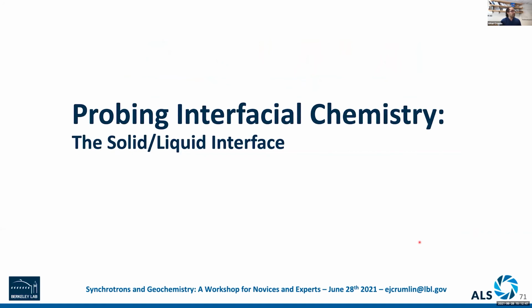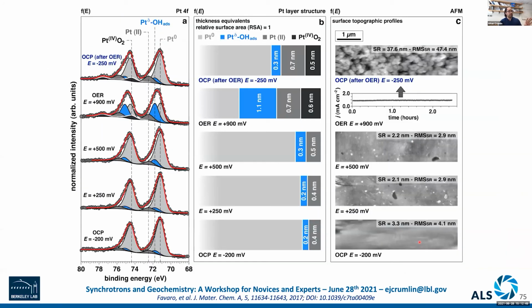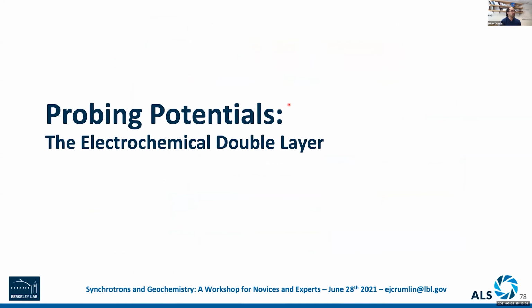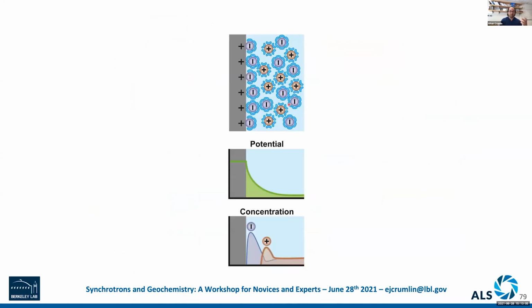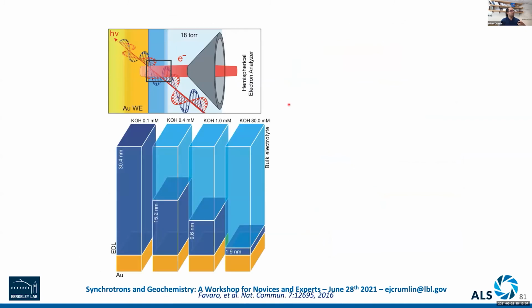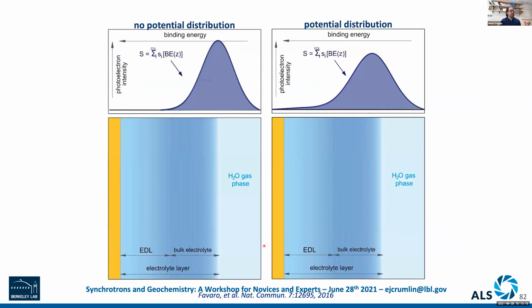And so I'm going to skip through this one, but essentially this is looking at the platinum electrode doing water splitting, where we can quantify the different thicknesses of this layer as it's evolving and get a clear picture of what is happening as it's all changing spectroscopically. And what I want to do is go quickly to the electrochemical double layer. We can sense potentials. If we use this technique and we create different thicknesses of the electrochemical double layer, effectively, we can now use the potential sensitivity to probe this.